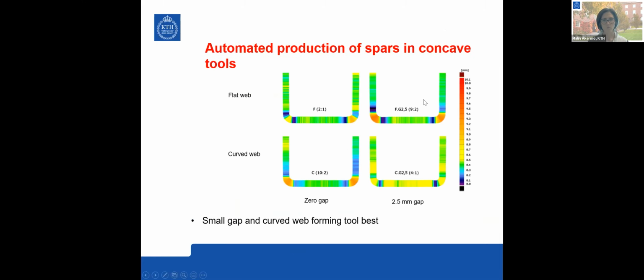Doing this, we could actually see that if you have a small gap and a slightly curved web, as what we see here, the colors become more unified, which means that there is a small difference in thickness after curing, compared to the others. So this scale here shows the thickness scale.